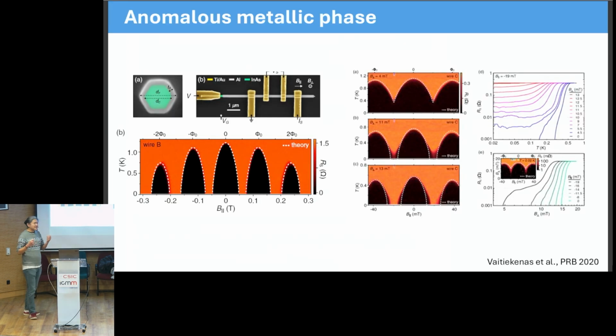Okay? So the wires I'm talking about are a semiconductor, in particular indium arsenide, and they're covered by a superconducting layer. And typically, when we do transport experiments or make any device, we have to contact these nanostructures with some kind of electrical contact. Many of the studies that have been done in this kind of nanowires, and there have been many, use normal contacts, typically gold, to contact these nanowires. Well, up to, I think, our work, people and us included have completely overlooked what happens at this interface. So is there any kind of impact of the normal contacts on the superconducting properties of this nanostructure?